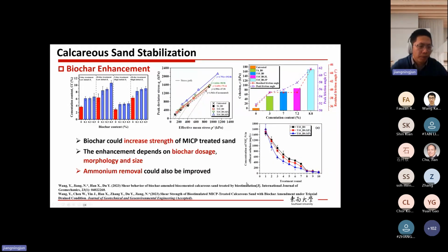The first graph shows different biochar contents from 0.1, 0.3 to 0.5. Compared with the no biochar case, the cementation content increases. And this is true for different treatment schemes and different initial soil densities. So this result shows that biochar could improve cementation content. This is very important.